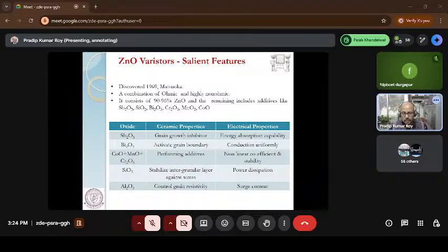Now, if you look at the function of varistor, as I said, initially insulator, then conductor, then again insulator. That is done only because of the presence of bismuth. This bismuth is basically an insulating oxide material, which acts as an activator of grain boundary. I'll explain what that activator of grain boundary is. It is also responsible for conduction during the surge. Antimony oxide is mostly used as a grain growth inhibitor, which means you have to control the grain size during the operation, and electrically it increases the energy handling capability.